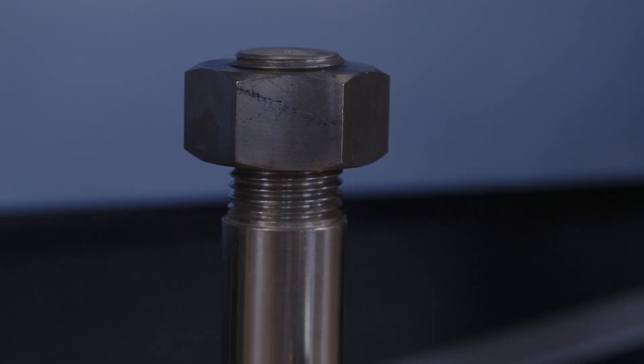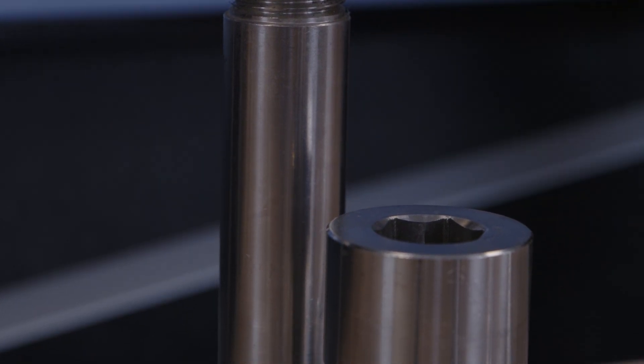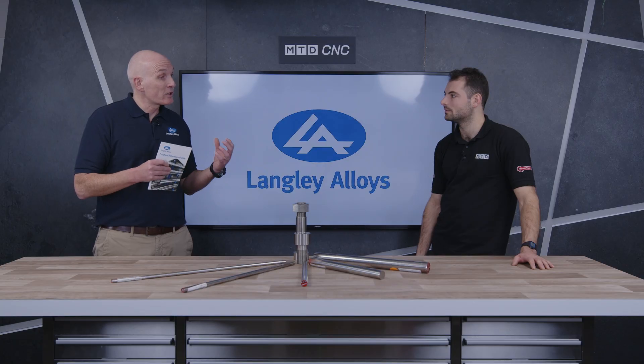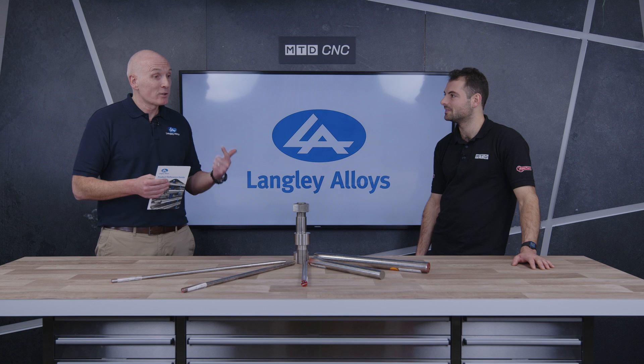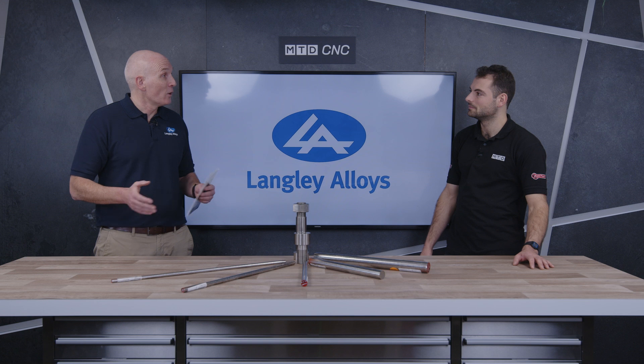Because of those properties, you can probably give a little summary. You've brought some fasteners here and some small diameter parts — what are the applications of this grade? Without going over too much old ground, it's a grade based on 25% chrome content, which gives it great corrosion resistance. The combination of two different types of microstructures — why it's called duplex or super duplex — gives it great strength and mechanical properties. Its composition is carefully controlled to achieve those properties without introducing too much cost. So you've got good strength, good corrosion resistance, and good cost competitiveness.